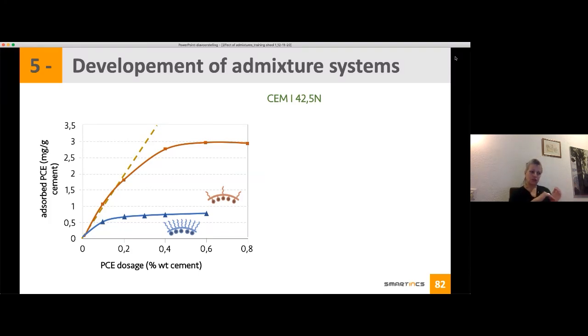In the first case, you have a small increase, and then you have a plateau. So the more you add, it won't adsorb more. For some reason, because of the chemical structure of your PCE, it won't adsorb on your cement. And usually you say the more PCE, the more workability. But these measurements are interesting to know because, for instance, in the case of the blue PCE, you say, okay, at 0.4 I still don't have enough workability, I want to go higher in dosage. You should not do it because it won't help the dispersing effect of your cement. And if you have too much PCE in your system, so overdosage of your admixture, then you will have segregation and not a homogeneous and stable system.